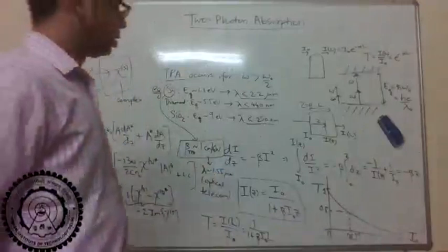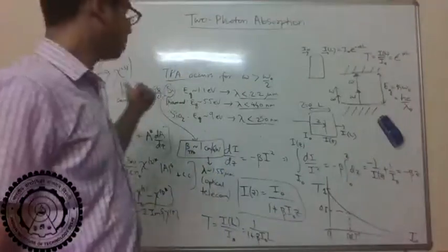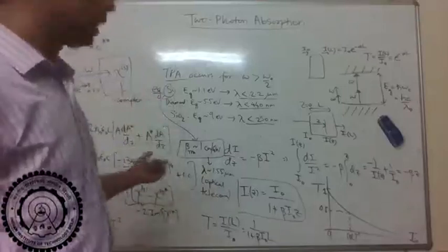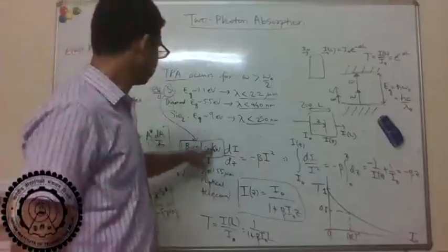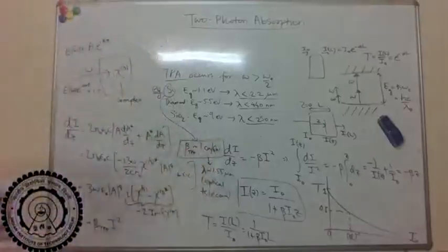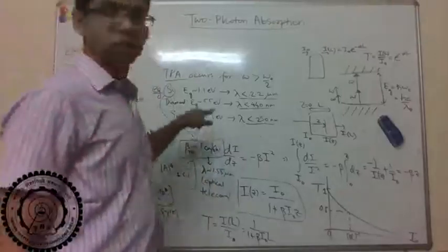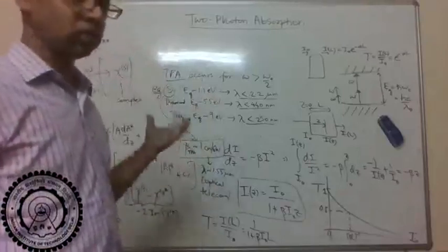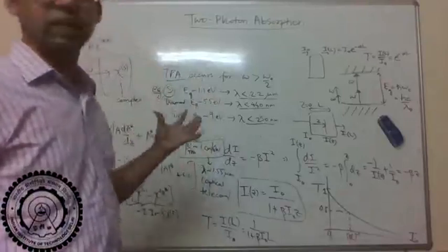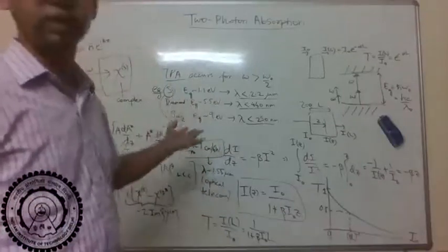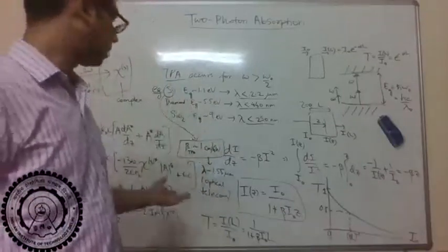And so people want to make all optical devices using silicon now, which can be applied to optical telecommunications. But one bottleneck is basically that silicon has a fairly high two-photon absorption at this wavelength. So it has a very large n2 also, if you remember, like the real part, which gives the intensity dependent refractive index. And that's sort of the real part of chi3 is what we can use for different interactions. So we'll study, for example, four-wave mixing a little bit later.